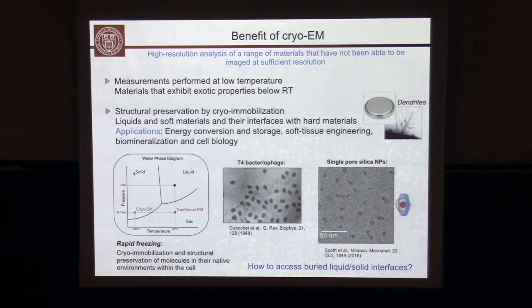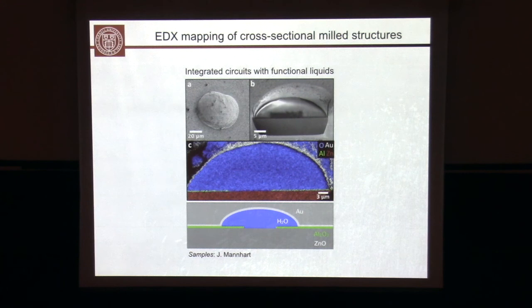Now, this works really well for very thin samples, so for example, proteins, right? And that's why this hype about cryo-electron microscopy, they have reached 2.1 angstrom in understanding the structure of a protein, which was celebrated as a breakthrough. Now, in batteries, we have extended objects. So how do we access buried liquid-solid interfaces? One simple way of doing that is using a focused ion beam mill, which is basically you focus an ion beam and use that ion beam to machine your sample and create cross-sections through that sample while maintaining the sample at cryogenic temperature. So we combine a cryogenic stage with a focused ion beam, and that lets us cut through liquid-solid interfaces.